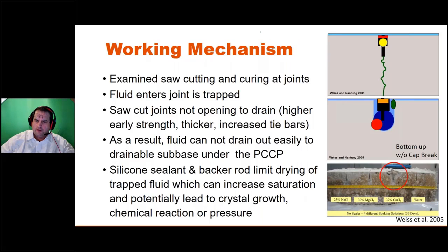So over time, we developed a little bit of a working mechanism. This is primarily developed out of what was done in the state of Indiana, but the whole idea is they come in very early and put a saw cut in. The second step is that we get cracking in the pavement. That crack essentially helps us to stabilize the width of the joint. They come back, widen the saw cut, and put in the backer rod and the sealant. When all this is done well, it keeps the fluid from getting into the joint. But as was discussed in our previous talk, it's all too often that this sealant didn't work really well. So the sealant detaches in some way, and fluid gets into the joint.